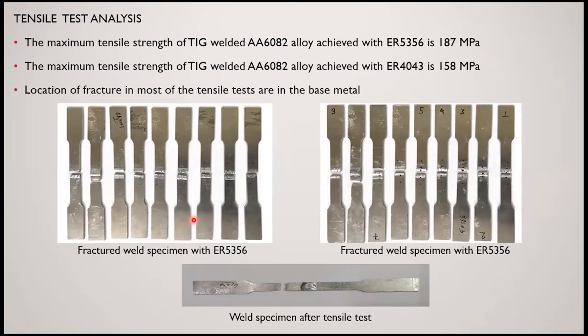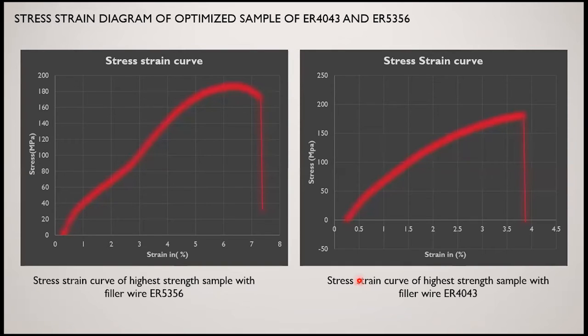These are the pictures of the fractured weld specimens after the tensile test. And this is the stress-strain curve for the fractured weld specimens with ER5356 and ER4043. Here we can say that we are getting maximum strength with ER5356, and yielding takes place in ER5356. As we can see in the graph, there is a sudden failure with ER4043. So we can see that we are getting good strength with filler material 5356.